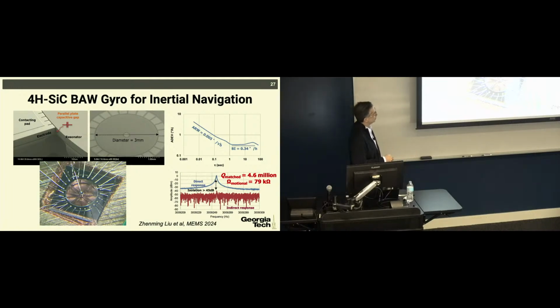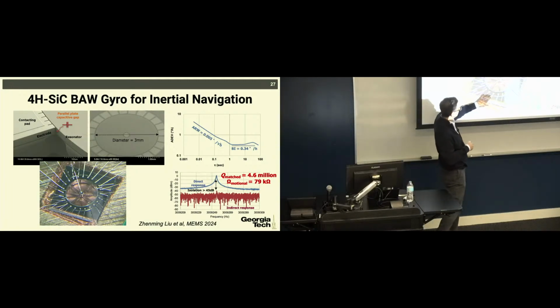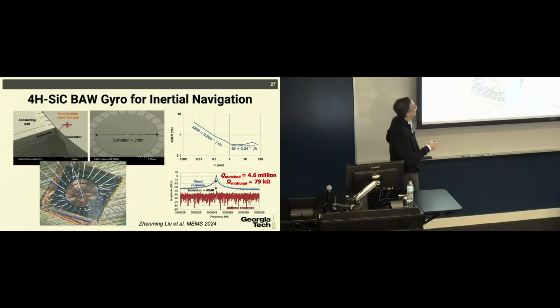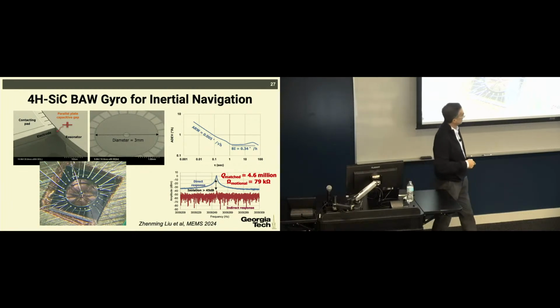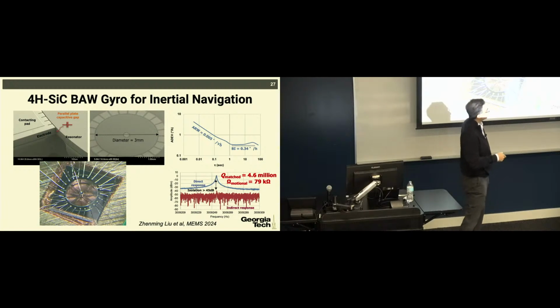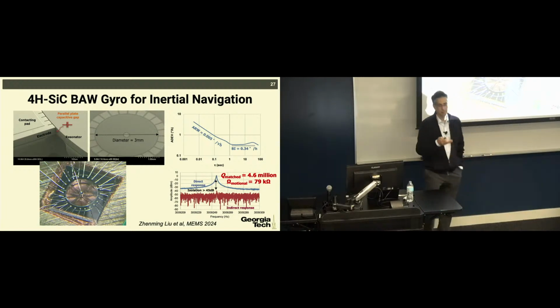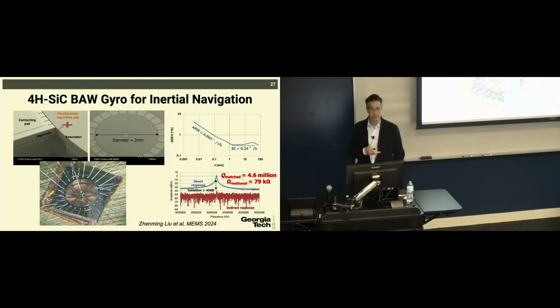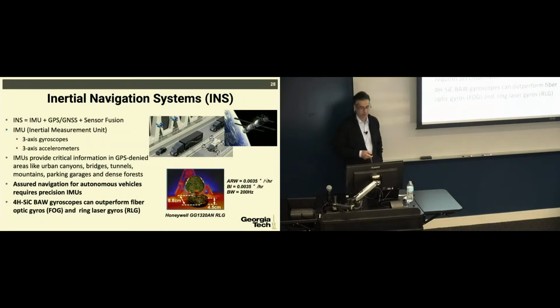This is a silicon carbide disc resonator. It's a disc gyroscope, and you see the process is so well developed, you can wire bond to all of these pads. This is the SEM picture of the device, and this is how smooth the side walls of the silicon carbide are. And the device, about 3 millimeter in diameter, shows a Q of 4.6 million in the mode match condition, and an ARW that is now about 10x better than what I showed in the silicon device earlier. Okay? Now, why is this important?